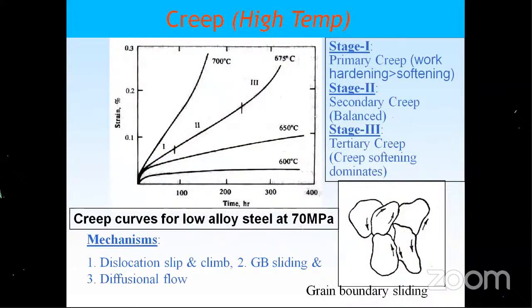One of the important things about high temperature is this creep issue, which in space we don't have an issue with, but even then you should know about creep. Creep is nothing but deformation at different temperatures at a constant stress. You can see at 70 MPa, 600 and 650 degrees centigrade, we don't have much issue. But when you go to 675 and 700 degrees centigrade, the material deforms. Some of the mechanisms are dislocation slip and climb, grain boundary sliding, and diffusion flow. One of the prominent ones is grain boundary sliding. So we make a coarser grain material so that grain boundary sliding will be difficult. This is the principle of single crystal and coarse grain material.